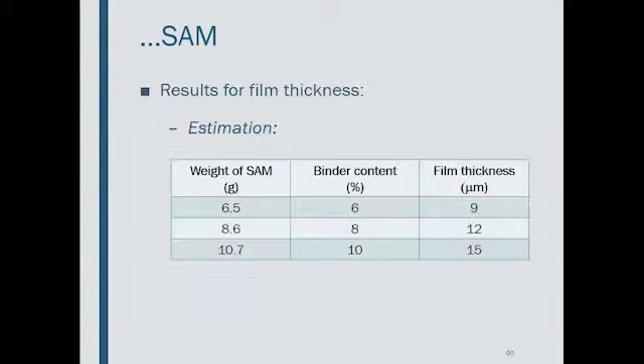And about the film thickness, these are the results for the estimation. So we believe that we are in this range, about 9 and 15 micrometers. And we suppose that with this, we are close to the real in the field.